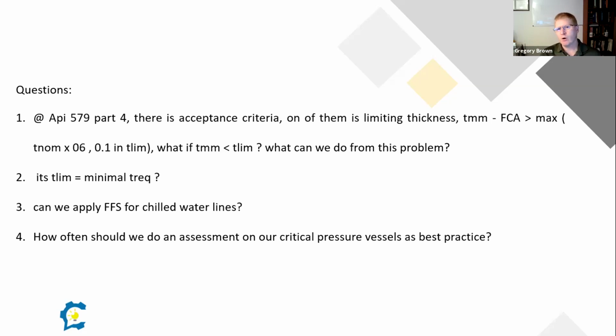So what that means is for our carbon and low alloy steels, as we operate colder, we have less resistance to cracking. That makes small cracks that might have been acceptable at ambient conditions at 20 Celsius not be acceptable at lower temperature. So yes, you can apply fitness for service to those equipment. Now, from your question, I don't know what type of fitness for service we are doing. Are we looking at metal loss? Are we looking at cracking? Are we looking at fatigue, etc.? But absolutely, you can apply fitness for service in those conditions.